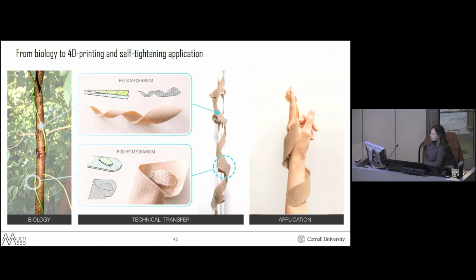And so this is a summary of the biomimetic process. So we take this tensioning strategy from the air potato plant, which was abstracted and then transferred to 4D printing through the design of those two mechanisms, the helix and the pocket. And we can individually tune those mechanisms and combine them into a single material system and evaluate them for applications where the fit and grip are important.